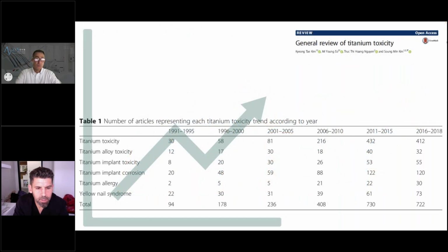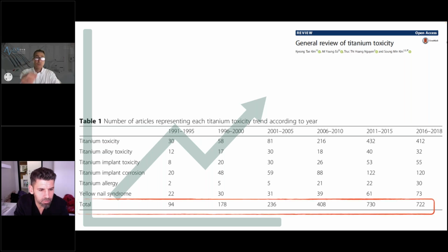This is an interesting paper that reviewed the incidence of titanium toxicity. What is interesting is that if you look at the bottom here, in the period between 1991 and 1995, there were about 94 publications talking about titanium toxicity, whereas in the last period, 2016 to 2018, there are now over 700 publications related to titanium toxicity. Now, this is data from both the orthopedic and dental literature. In fact, the orthopedic literature is more abundant when it comes to titanium toxicity. There are a lot of issues with hip, shoulder, and knee prostheses, and so our orthopedic colleagues are also aware of this titanium toxicity.